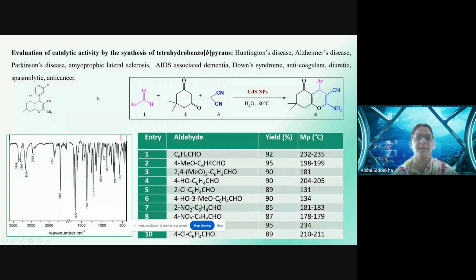In the application part, we evaluated these for a multi-component reaction using aldehydes, dimedone, and malononitrile to prepare a series of benzopyrans, and we used different aldehydes here. They were obtained in very good yield. The reaction was carried out under reflux in water at 80 degrees, and since they are heterogeneous catalysts, it was easy to remove them. The product was dissolved, and the purity was checked by TLC and found to be very good. Here I have presented the IR of one of the molecules that we have prepared.